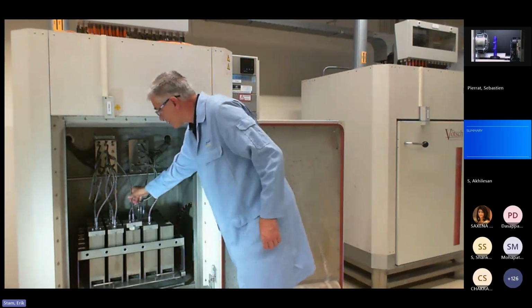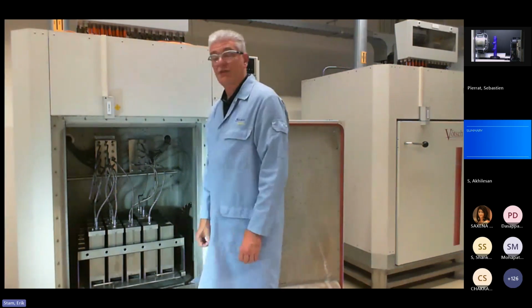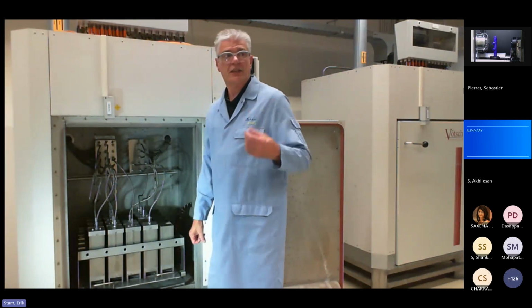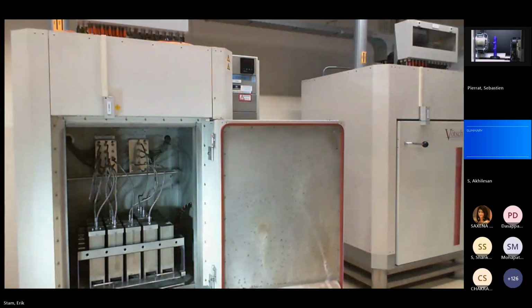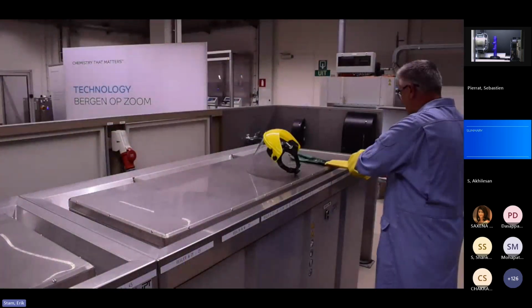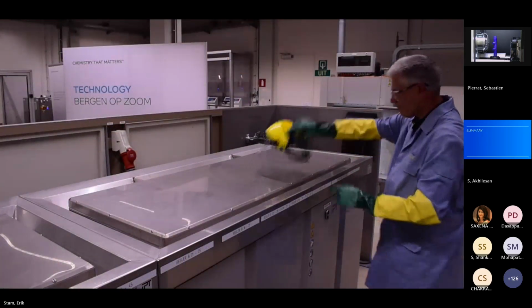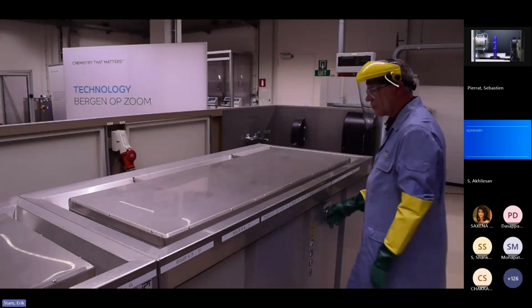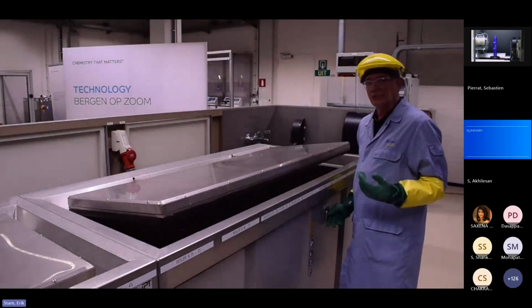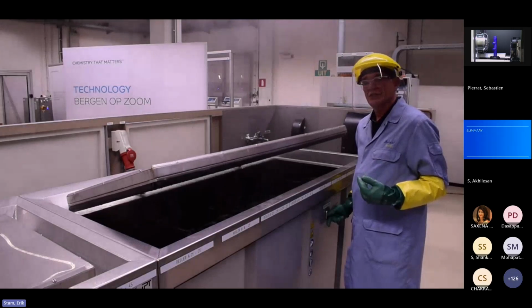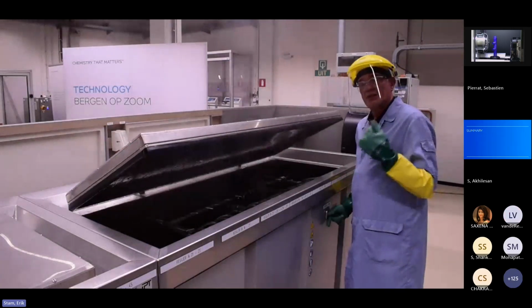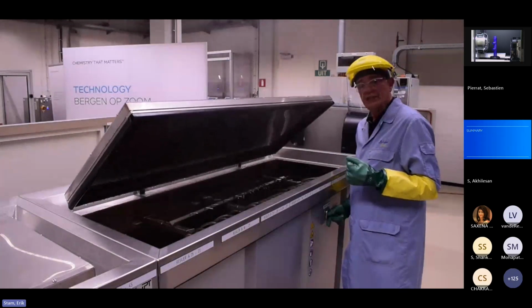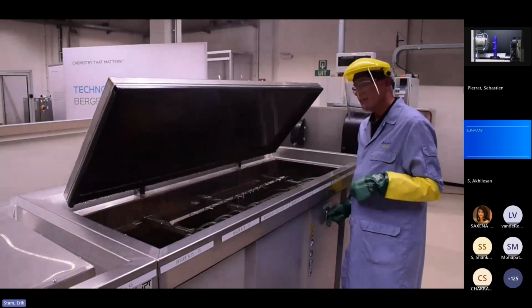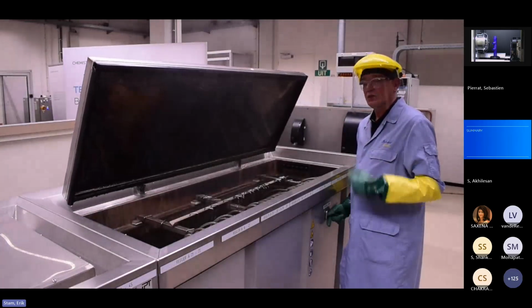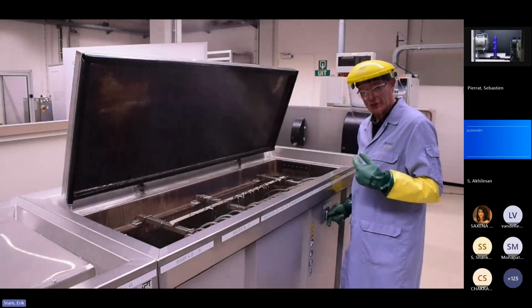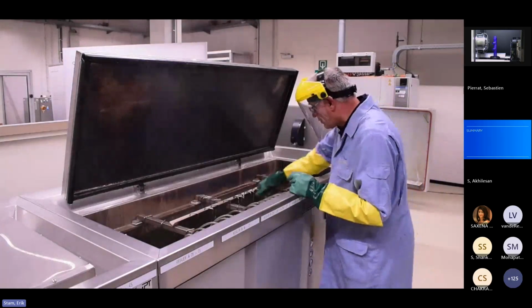Yeah. So this is about fatigue testing, but it's also very important to understand the constant pressure resistance. And for that, I will move to the next setup. Constant pressure resistance is often called creep rupture or long-term hydrostatic strength. This involves that you expose the inside of an application or a pressure vessel to a constant water pressure, and you continue until the material or the application fails due to a phenomenon which is called creep rupture. And I will show you one sample.